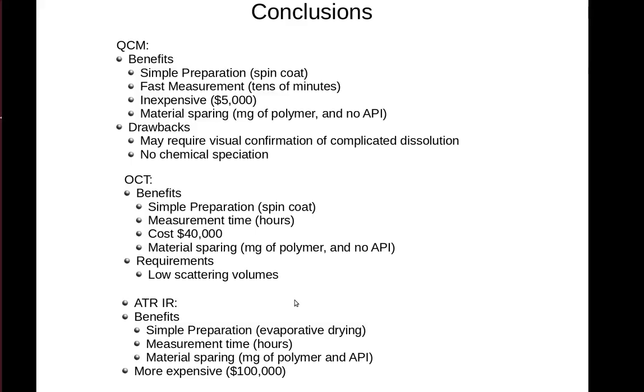So in conclusion, some of the benefits of the QCM are very simple sample preparation. We can simply spin coat the polymer. It's a fast measurement, tens of minutes, and it's inexpensive. The instrument costs approximately $5,000, and a single crystal on the order of $10. So multiple crystals can be purchased, and DOEs run on them at the same time.